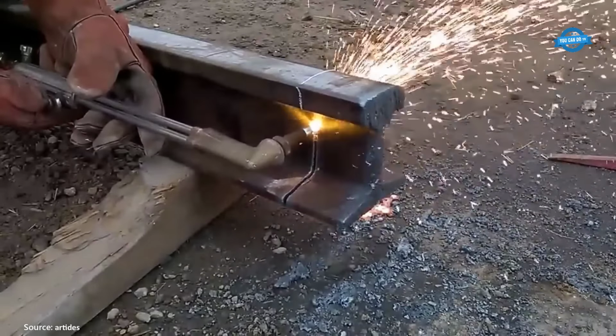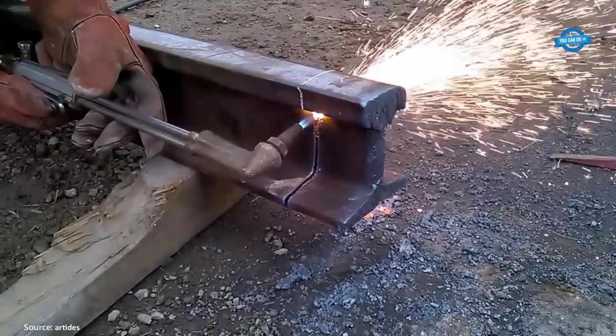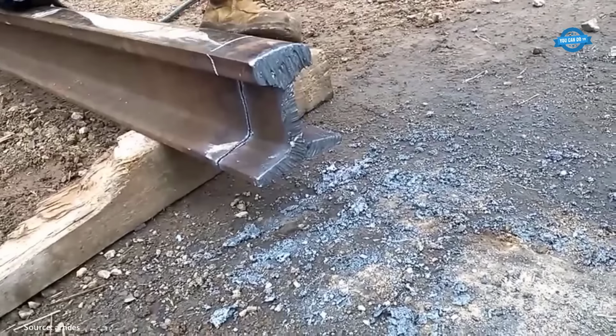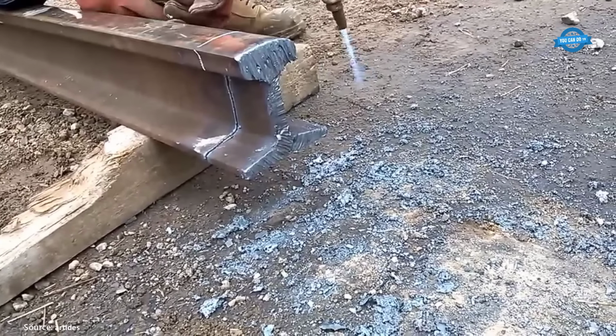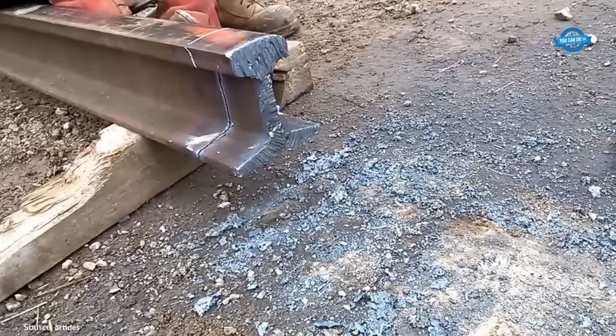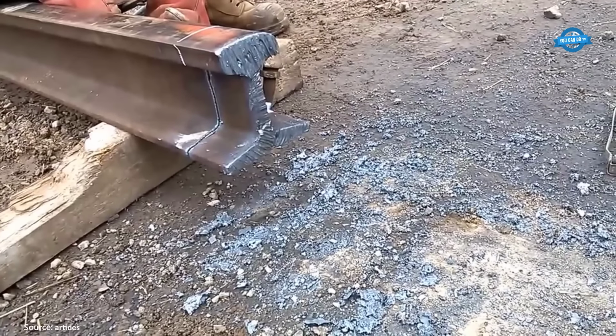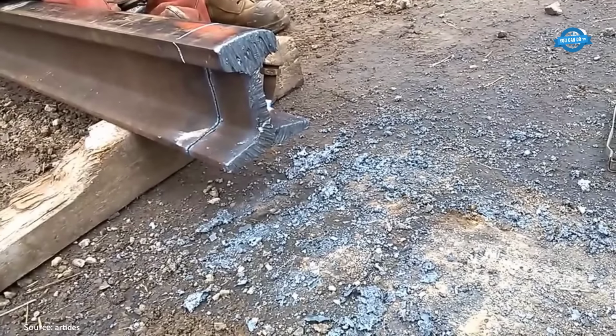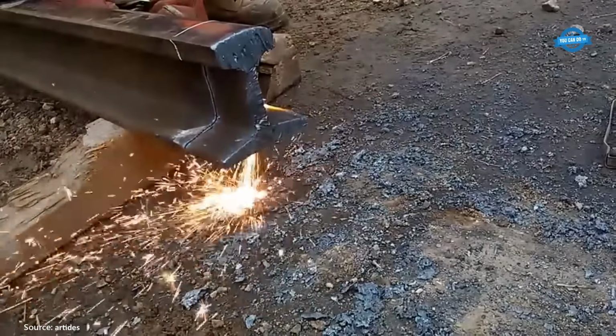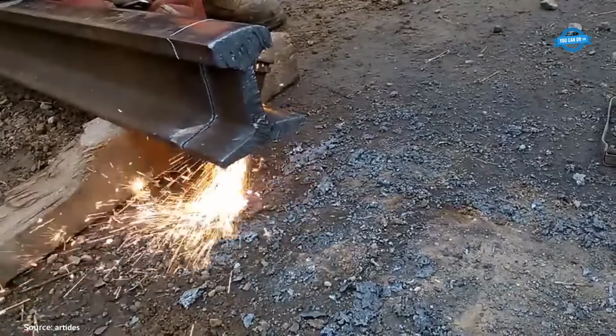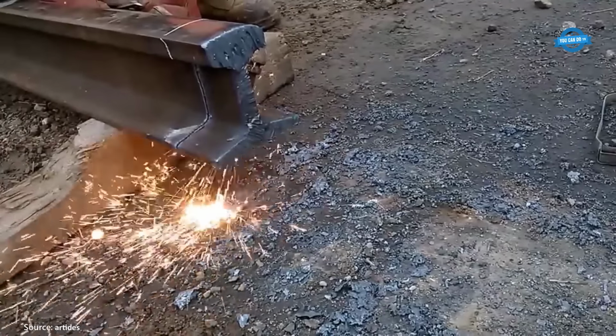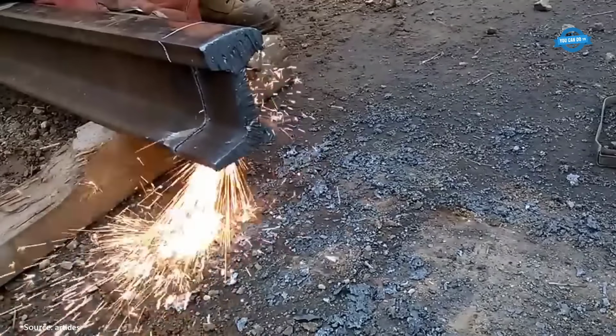The process starts with preheating. The flame brings the steel to its ignition temperature. Once the surface glows red hot, a blast of pure oxygen initiates the exothermic reaction, oxidizing the metal rapidly. Molten iron oxide is blown away by the same oxygen stream, leaving behind a clean kerf.